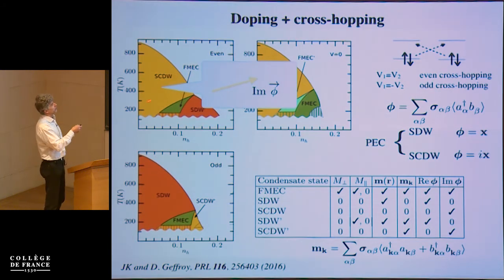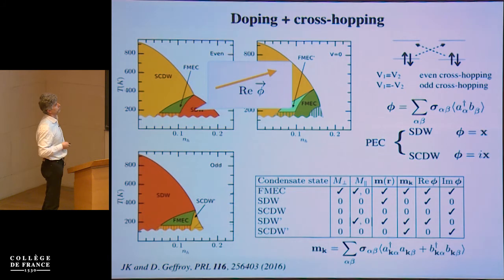We are going to get this current-like spin current-like order parameter at 0 doping, and then we dope. When we dope, we are going to go to the ferromagnetic phase and eventually to the spin density wave-like order parameter. So we will go from purely imaginary order parameter to purely real order parameter here.